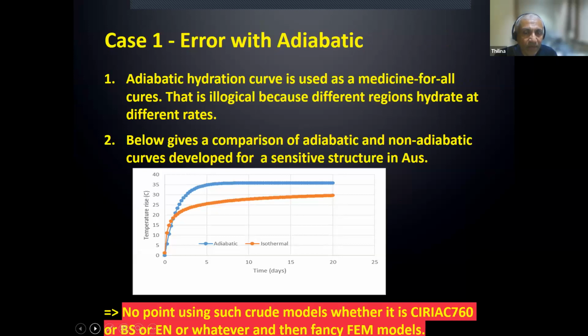This sample we have measured isothermal as well as adiabatic. You can see the 2 different curves. The green one hydrates faster, and the red one is slow. The red one represents a concrete zone near the external, exposed to ambient. The green one is the inside. So using a single hydration model, adiabatic, is incorrect. It has a place, but don't try to split hairs with fancy finite element modeling for sensitive structures. So as I said, there's no point using such crude models, whatever they are. Next one, please.